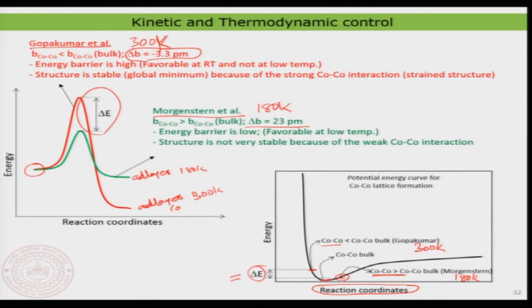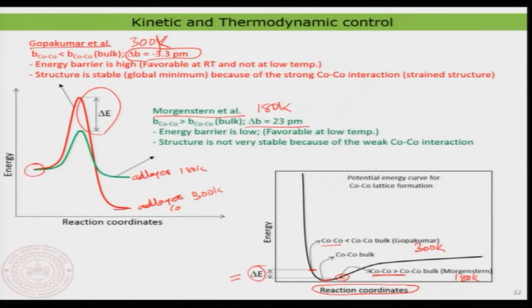So therefore, what happens when you deposit atoms, when you form the Adlayer at lower temperature, is that they would always go to some kind of kinetically controlled structure rather than the most thermodynamically favorable structure, because as you can see in the energy diagram, this particular case is the most thermodynamically favorable situation. So this is the thermodynamic control, and this is the so-called kinetic control: thermodynamical control and the kinetic control.